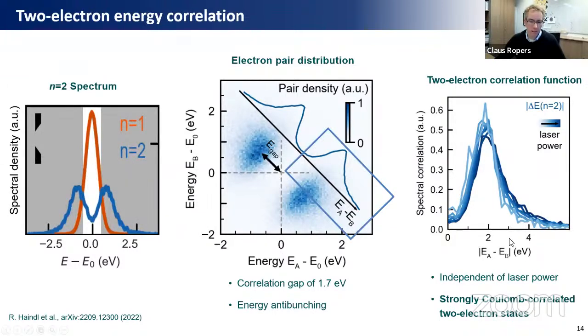First of all, I think it could be interesting and important for just fundamental considerations of photoemission processes. But there might also be an application of this because, as I said, we have more or less a random distribution of the rates of these events. But at the same time, the energy is very strongly correlated. And what this means is that this energy distribution actually allows us to exert statistical control over the number distribution of these electrons.